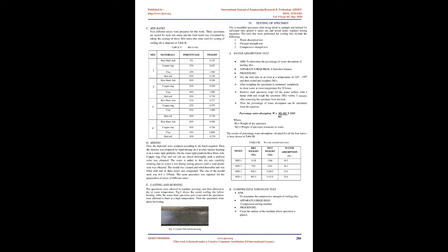Then the percentage of water absorption can be calculated from the equation. Percentage water absorption, W equals (M2 − M1) / M1 × 100. Mixing. First, the materials were weighed according to the batch required.